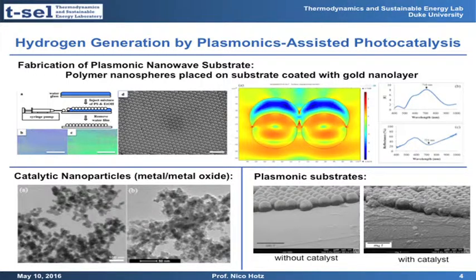And as you can see here in this COMSOL simulation, we have about a 7-8 times increase in electric field in the crevice down there in a very small spot of maybe 5 to 10 nanometer in size. We were not sure if that works because nobody ever has done that before, but we deposited our catalytic nanoparticles on top of these spheres to get this relatively rough, dirty-looking substrate here. And the good news is we got temperatures that were high enough to achieve chemical reactions.